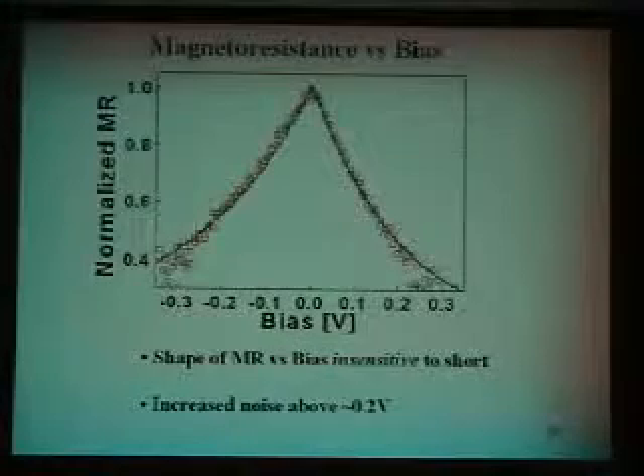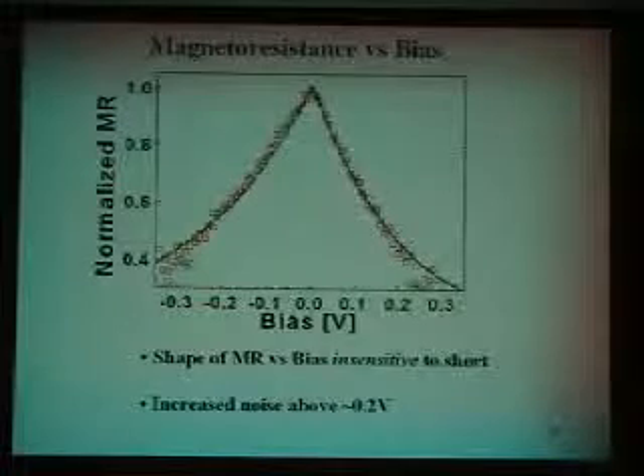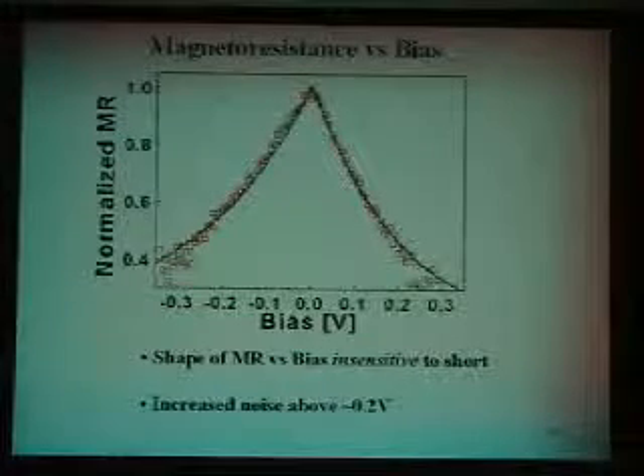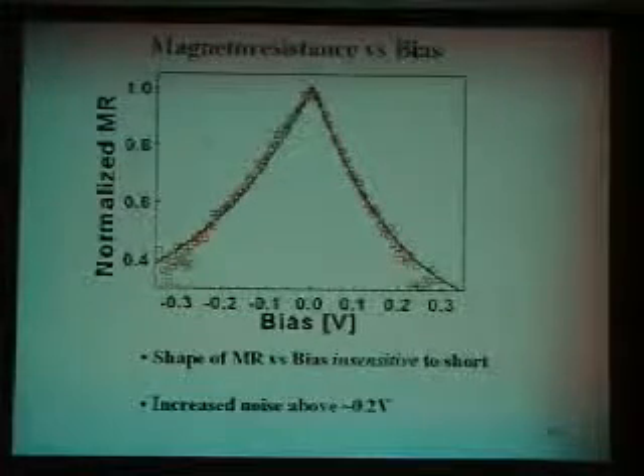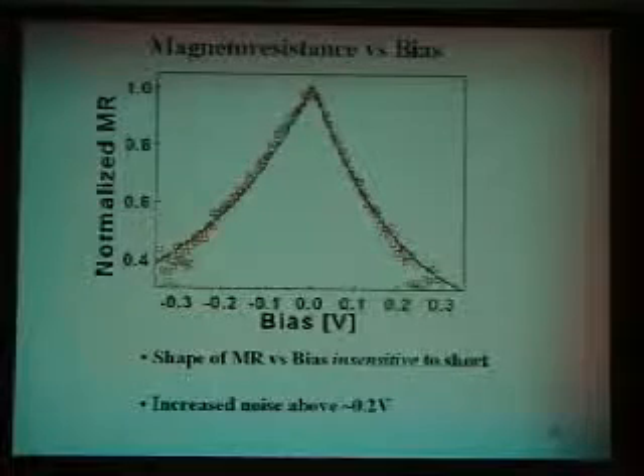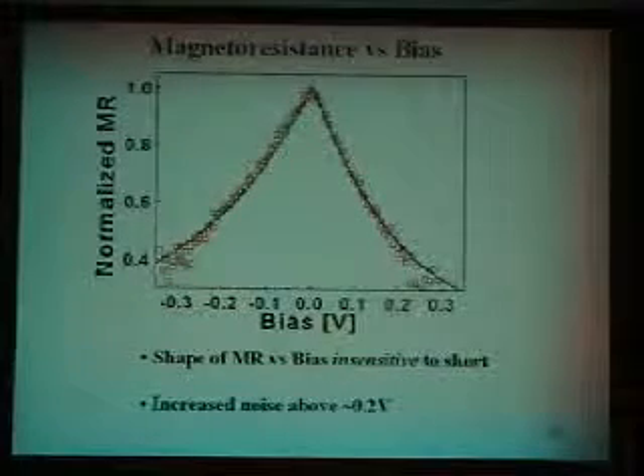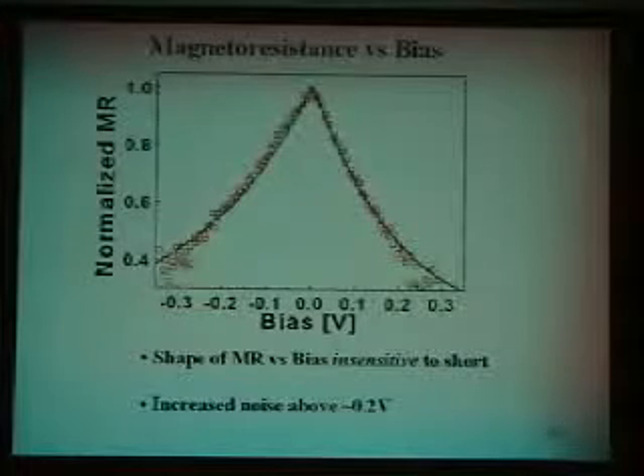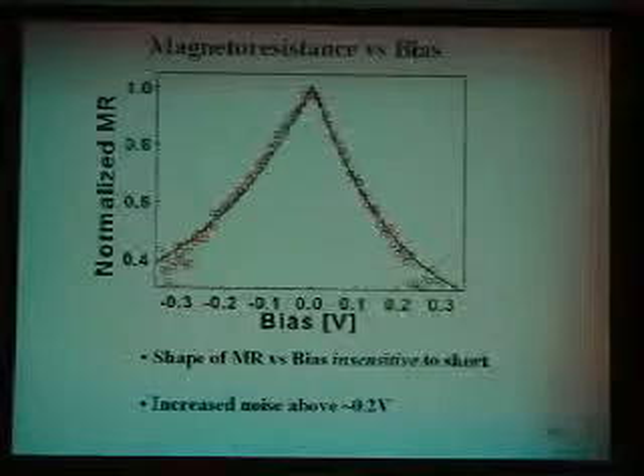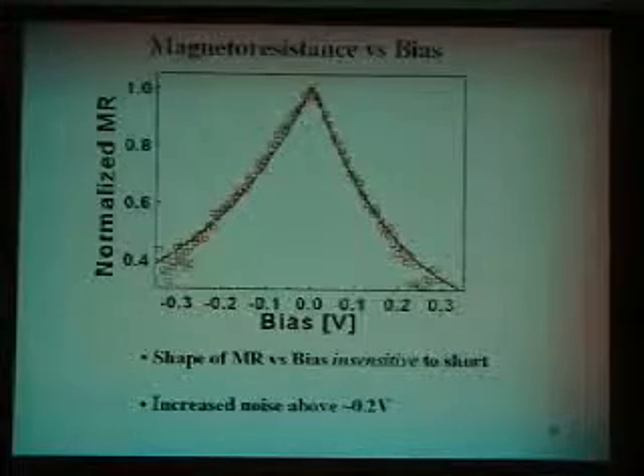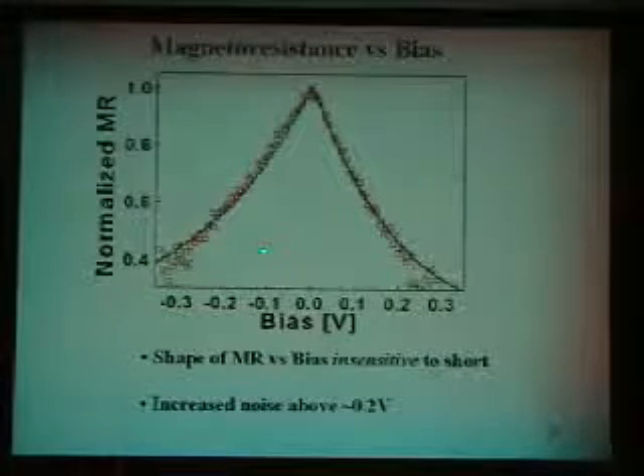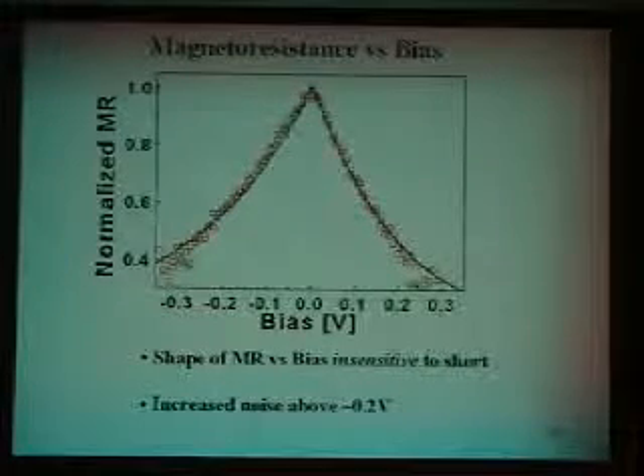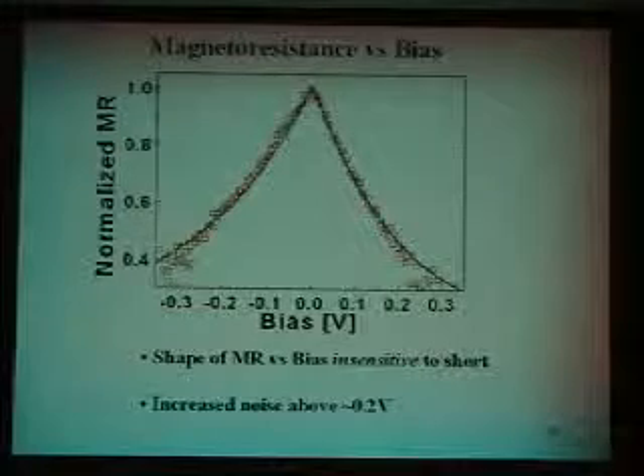And the shape of the magnetoresistance, you see, is insensitive to zapping. Okay? So the shape doesn't change, you see it again. It's as if you would have two resistors in parallel. You have a short, which is a metal, it doesn't do much, and this tunnel junction, which has a magnetoresistance. So the shape doesn't change because the shape comes all from this tunneling magnetoresistance.